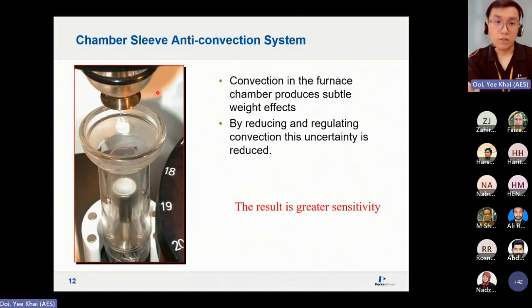Then we have anti-convection. Convection is a normal phenomenon, but it's something we don't want in TGA because this will give false positive or false negative results, caused by air turbulence or purge gas turbulence. Now in TGA, usually we use nitrogen as a purge gas. The gas coming in from the tank or from the nitrogen generator is usually cold. So when your sample chamber is heated up, it will take time for equilibrium.